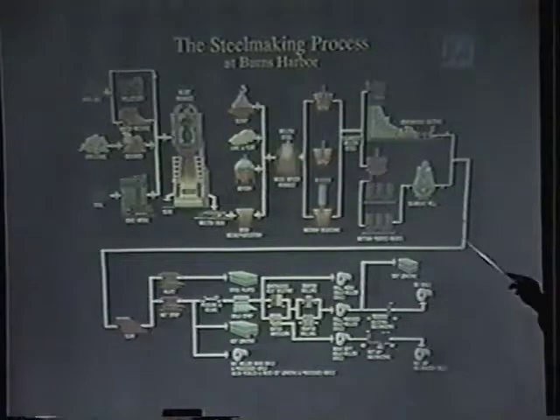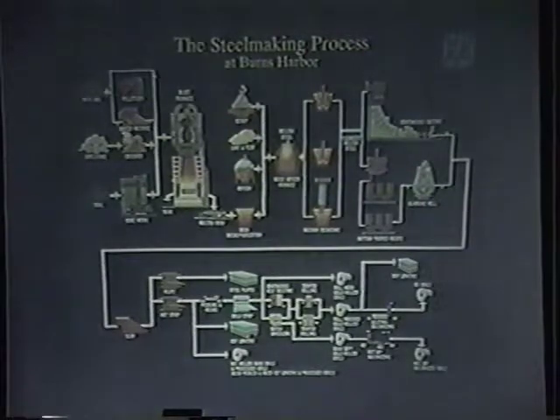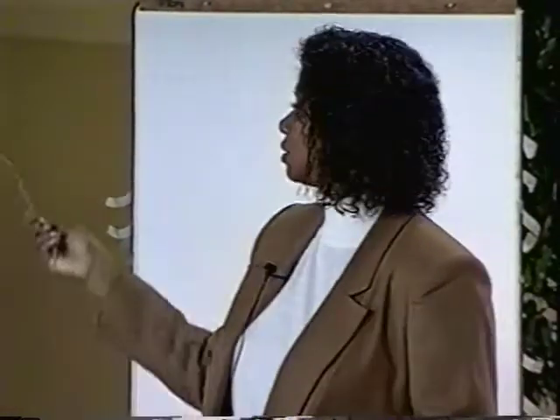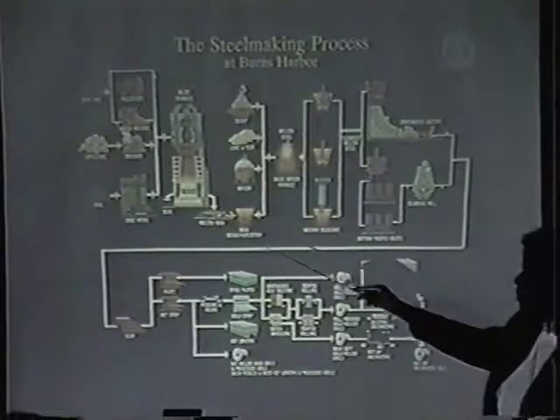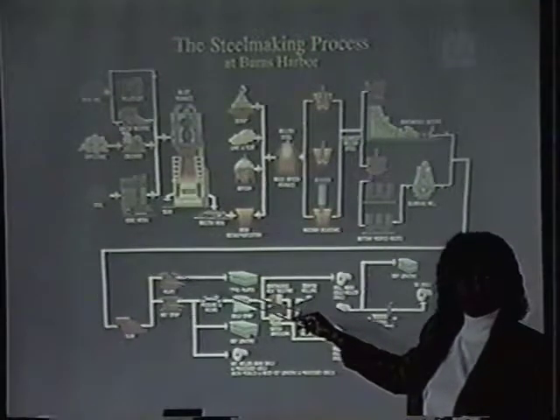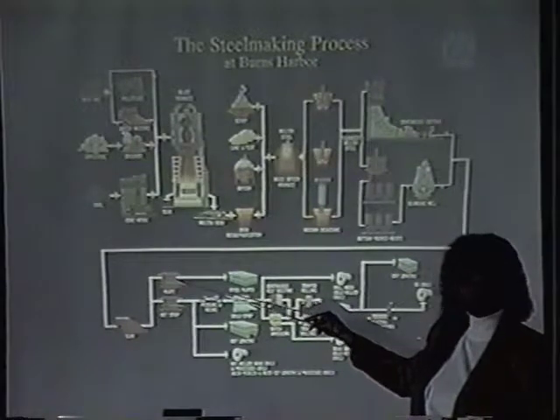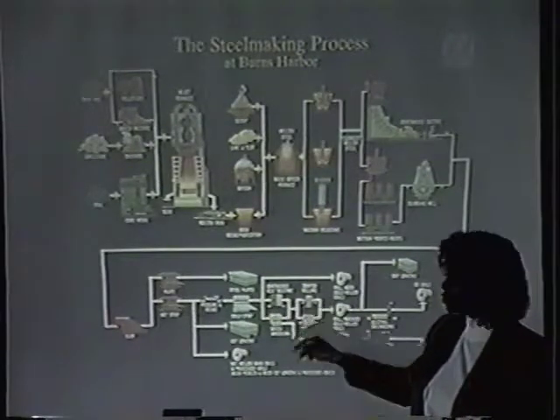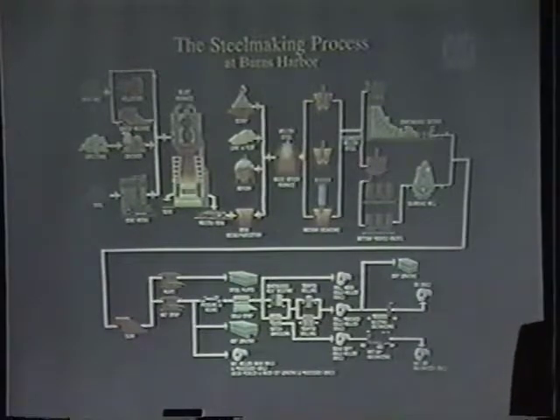So there's a vast difference in time of the two processes and yield. But the thing we have here is the ability to make very heavy gauge plates, which we have a market for at Bethlehem Steel. So we are using this method about 15 to 20% of the time for those specific applications that we cannot use the continuous casting method for. But once we have a slab by either method, it will go into our finishing mill operations, either the 160-inch or 110-inch plate mill, be rolled into a plate and shipped to our customer, or we'll go over to our 80-inch hot strip mill, where we will make a hot band.